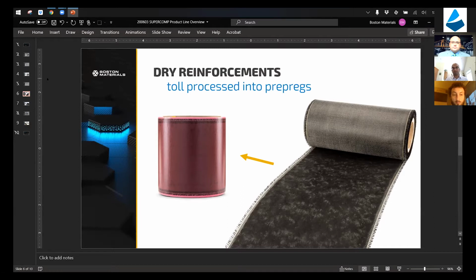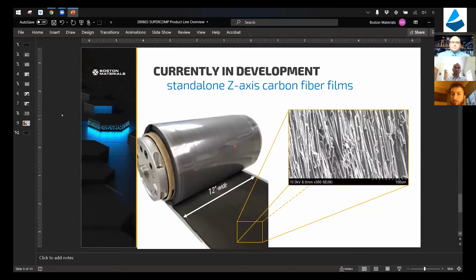For our work with thermoplastics, we processed polymers such as PEI, so Ultem, polycarbonate, PEEK, some pretty high viscosity resins. What we do is we melt and fuse a thermoplastic film into this dry carbon fiber structure. And in some of the new work that we're doing, we're coating thermoplastic films with the Z-axis material as the dry stabilized coating. Then we can infuse the underlying thermoplastic film, which we use as a web in our process, into the carbon fiber matrix, if that makes sense. So really no issue with thermoplastic viscosity. Really interesting. Thank you.